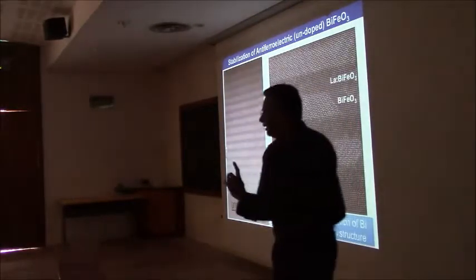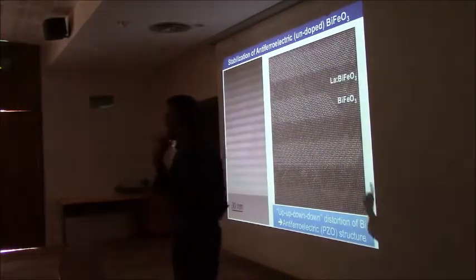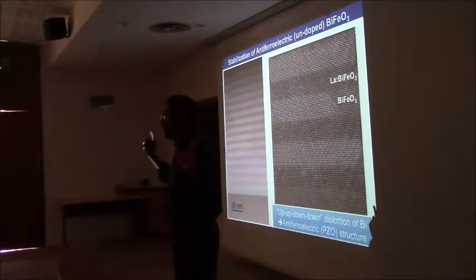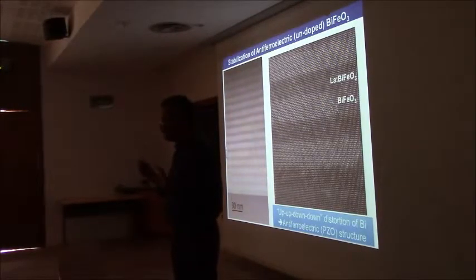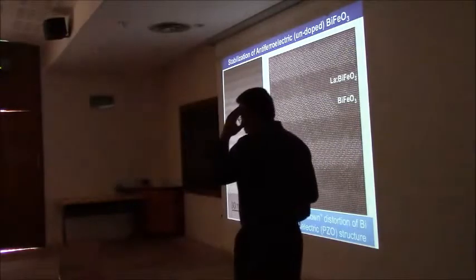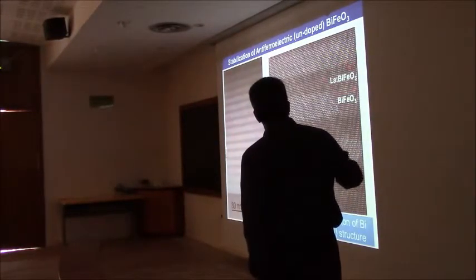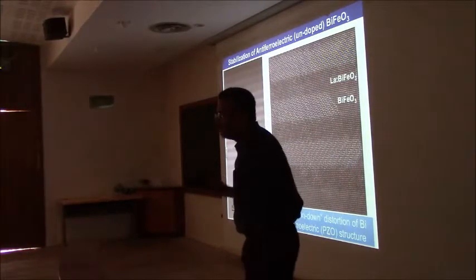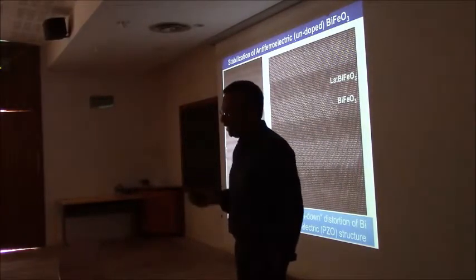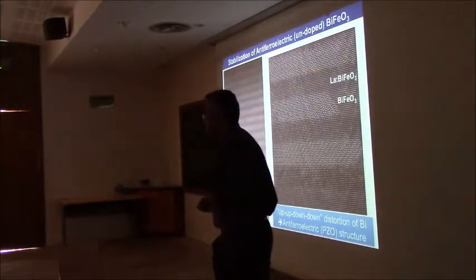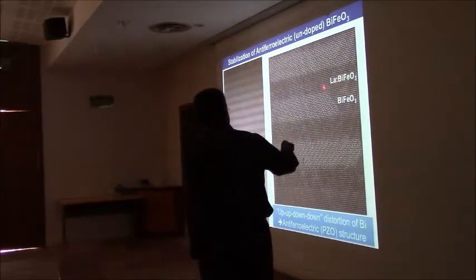Now, we said, let's not deal with strontium titanate, which is so different in terms of dimensions and stuff. Let's go to a known system. So this is where things went really crazy, and we're still trying to figure out. Let's take lanthanum doped bismuth ferrite. 30% of lanthanum in bismuth ferrite makes it non-ferroelectric. So it kind of looks like strontium titanate, but chemically it looks like bismuth ferrite.